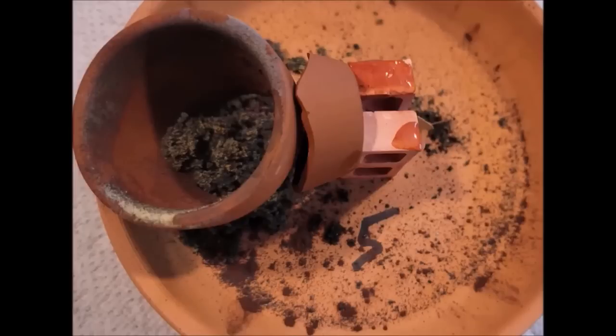This is what the sample 5 afterburn looks like. Note the unburned thermite both inside the pot and splattered across the tray, from which we can draw two conclusions. First, on the negative side of the ledger, this clearly was not an efficient burn. But second, on the positive side of the ledger, even with a burn duration 8 times longer than that of nanoparticles, there was still gas in the gas tank,